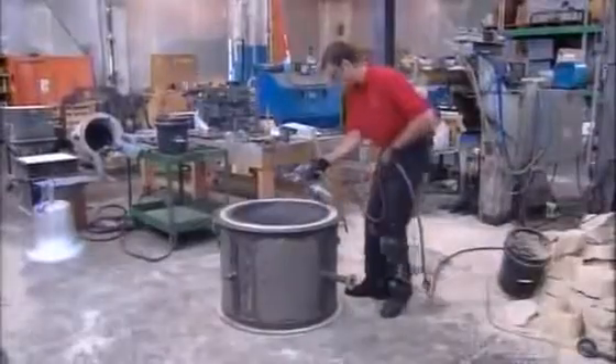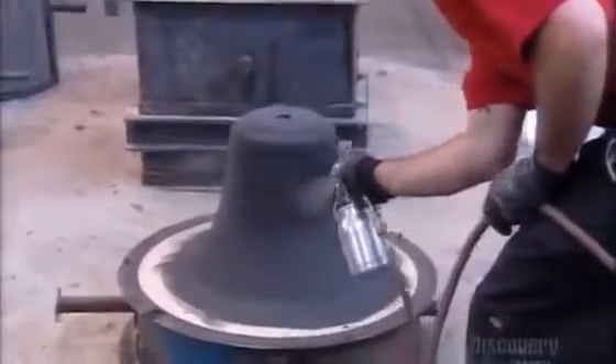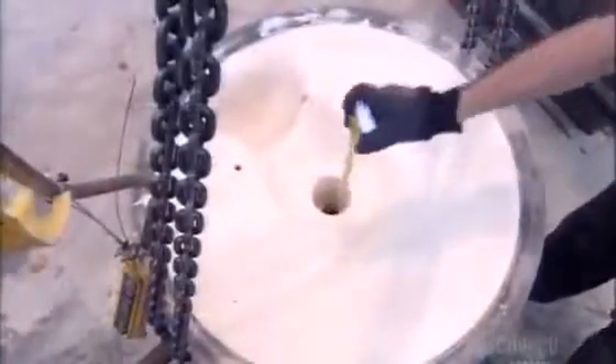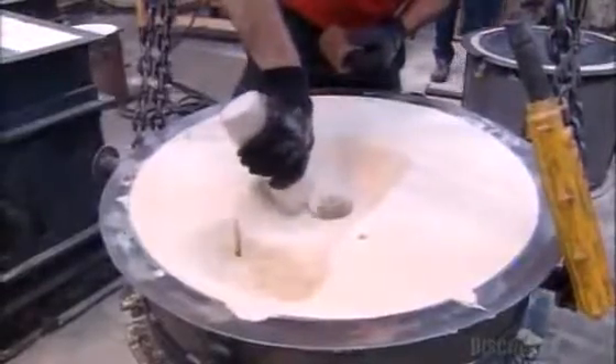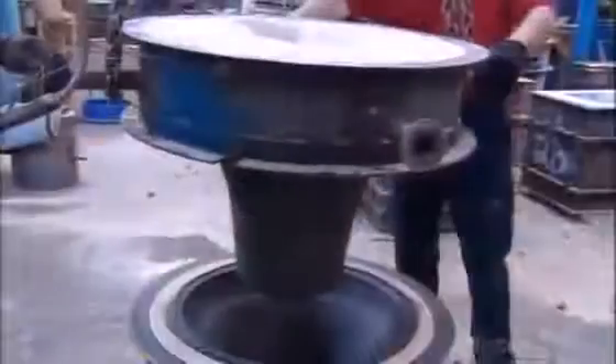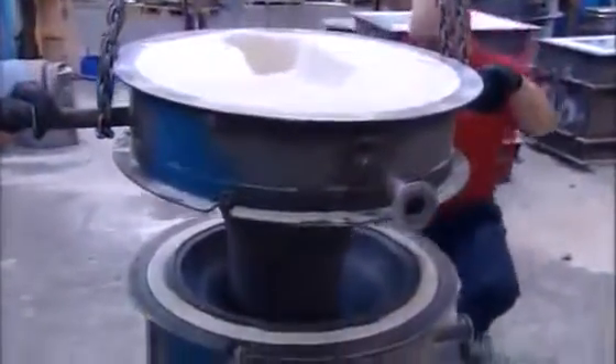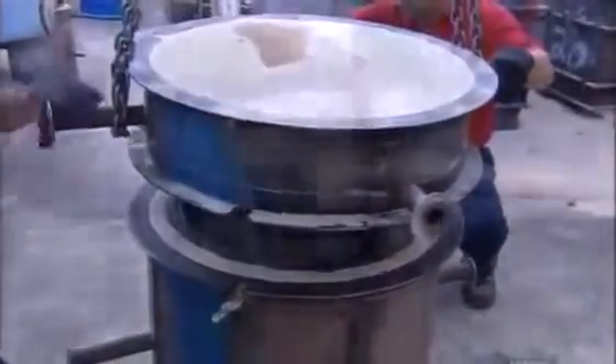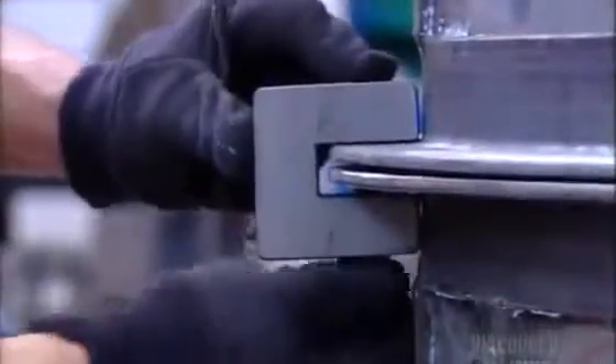Next, they spray on a second coat of wash. The sand is so fine that the mold would otherwise reproduce the brush strokes on the cast bell. Now they measure the size of the pour hole and custom make a ceramic filter to glue inside. This filter will screen out the slag, oxidized particles that form when molten metal meets air. Now workers stack the two mold sections back together and clamp them tightly so that the bronze won't leak out during casting.